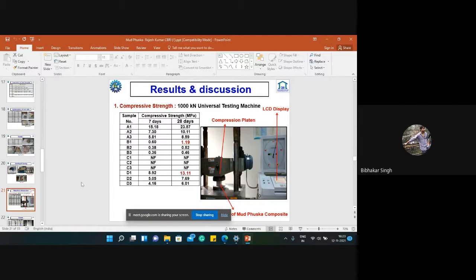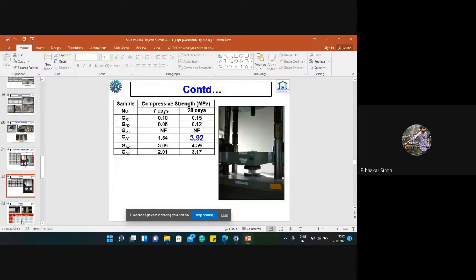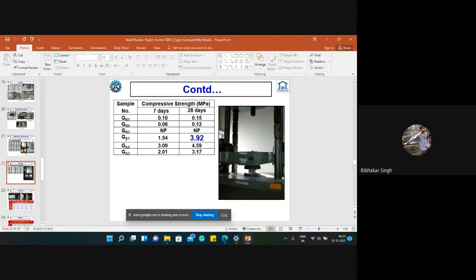So after analyzing all the results of compressive strength and other properties, we finally chose our sample GA1, whose compressive strength for 28 days is 3.92 MPa. We chose this lower compressive strength because for construction purposes, according to IS code, bricks more than 3 MPa are used for construction. And over the roof, when we apply the tiles, we can neglect the load bearing phenomena. So we chose GA1, designed with soil, crumb rubber, cement, and water.